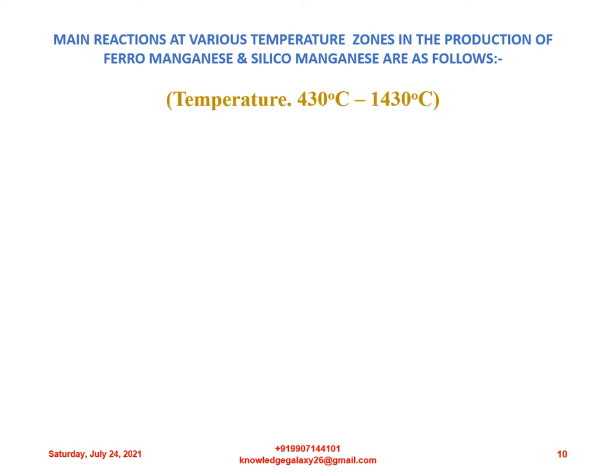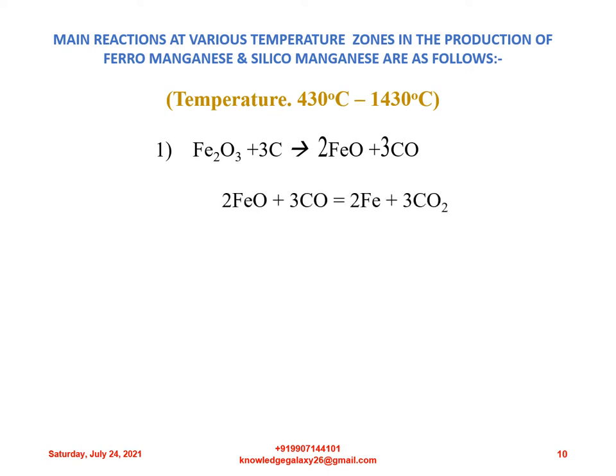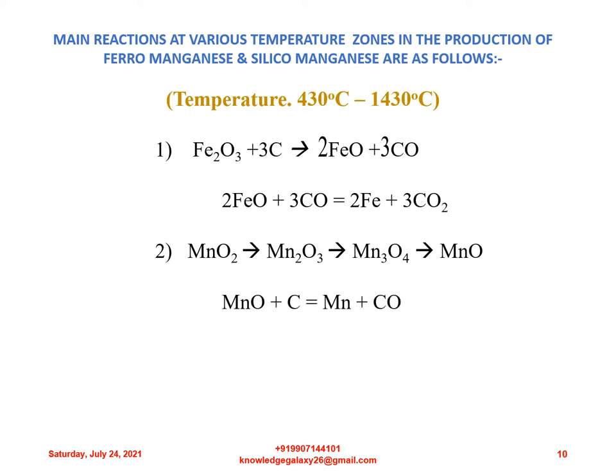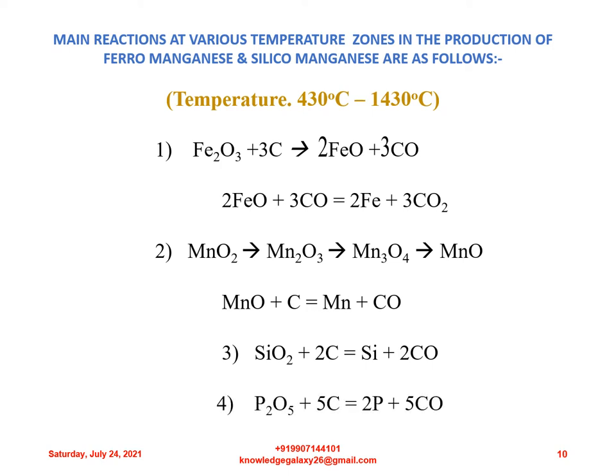First, the temperature range is 430°C to 1430°C. First reaction: Fe₂O₃ + 3C → 2FeO + 3CO; subsequently, 2FeO + 3CO → 2Fe + 3CO₂. Second reaction: MnO₂ decomposes through Mn₂O₃ → Mn₃O₄, and finally reaches as MnO; MnO + C → Mn + CO. Third reaction: SiO₂ + 2C → Si + 2CO. Another reaction: P₂O₅ + 5C → 2P + 5CO.